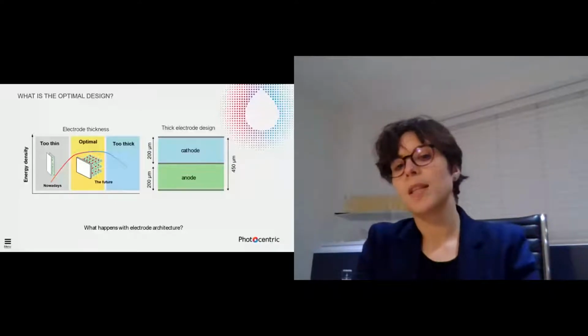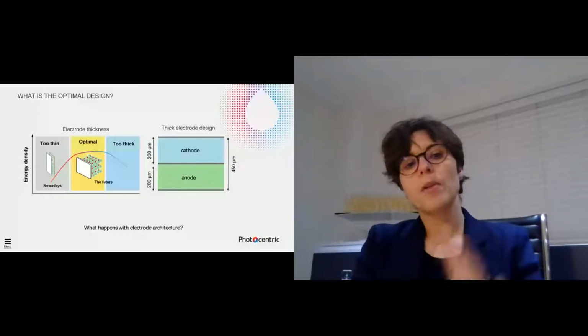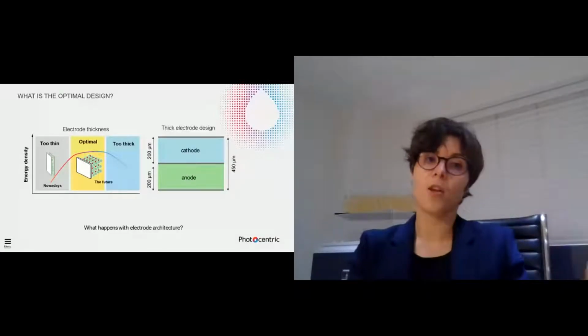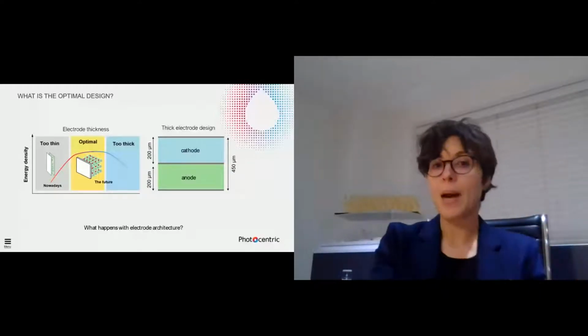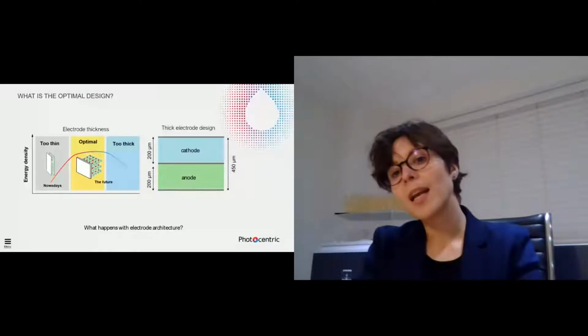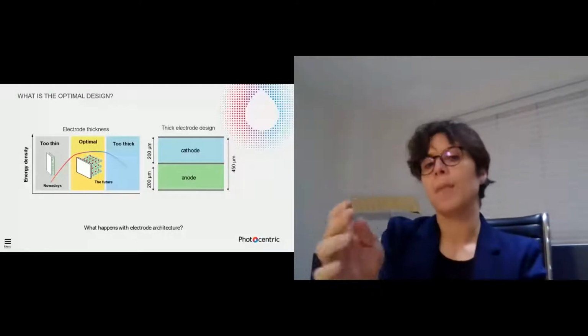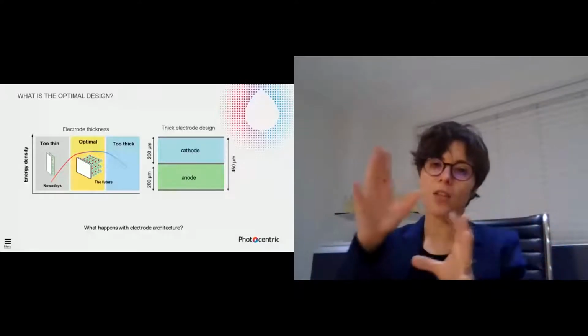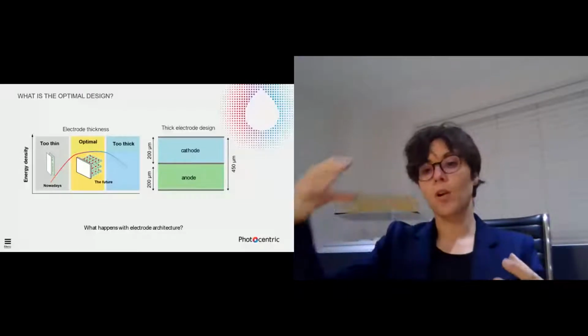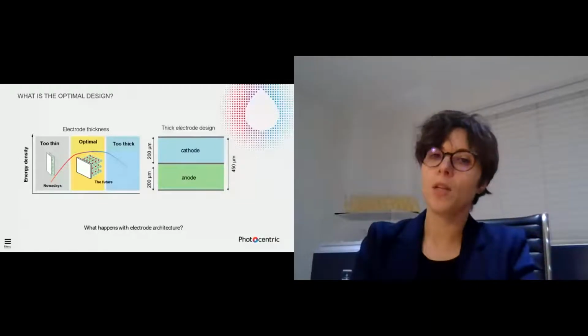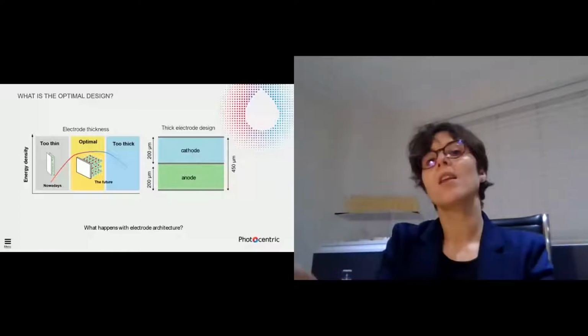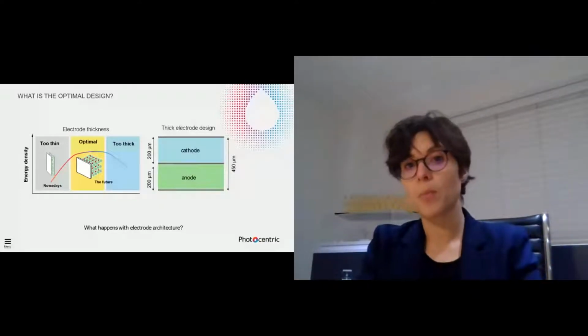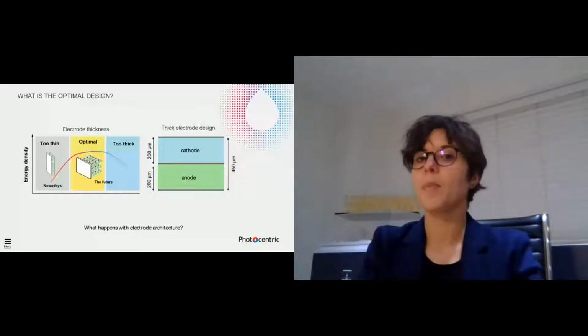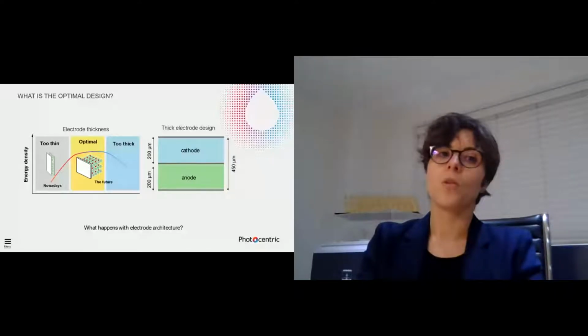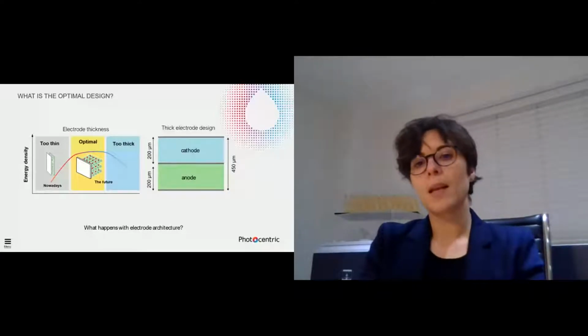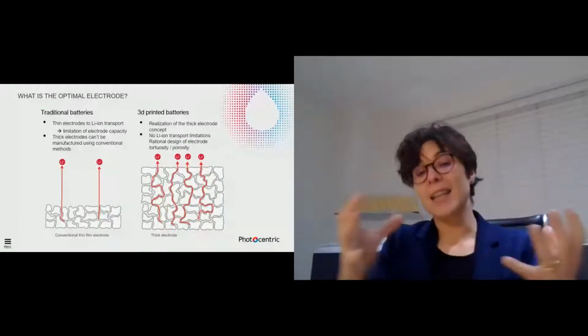However, there is a trick there, which is in the electrode architecture. We already saw that thin electrodes mean fewer lithium ions that can flow, and therefore they have a reduced capacity. However, whenever we talk about thick electrodes, you need to make channels for the lithium ions to be able to flow. You can picture it as having channels for lithium ions to flow through from the cathode over the separator to your anode. And that means that we need to design the porosity through which the lithium ions are going to flow. And this is possible with 3D printing. We can rationally design the tortuosity and the porosity of your electrode, so the electrode architecture, to make the best out of it and have the highest capacity possible.